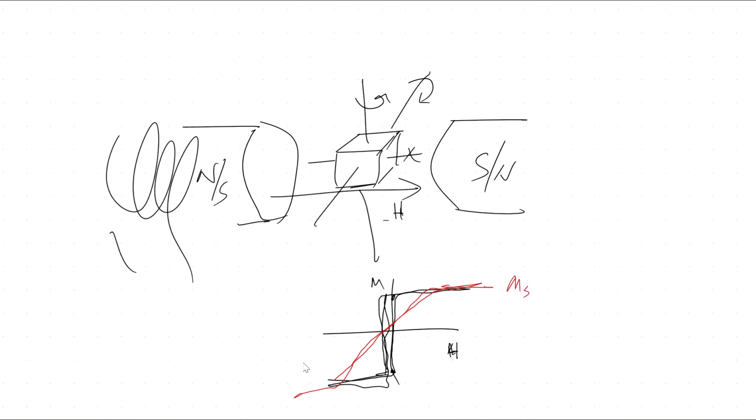This is saturation, plus minus Ms. But basically, it requires a certain magnetic field to get it saturated, and it implies that we are overcoming it. So if you take the bulk material and you see these different properties, then it might be that you have crystalline anisotropy.